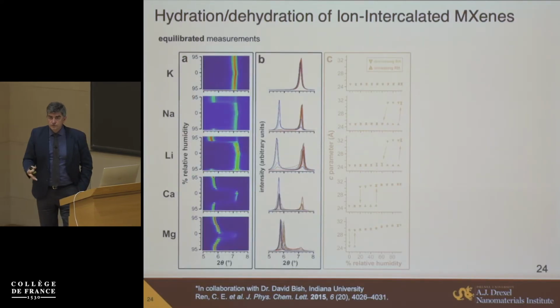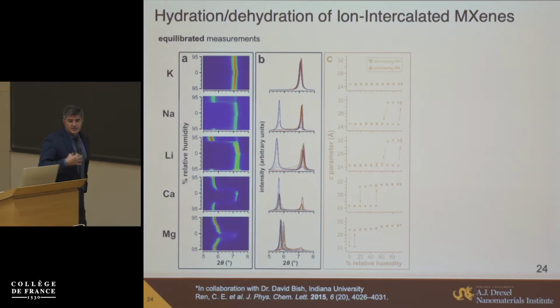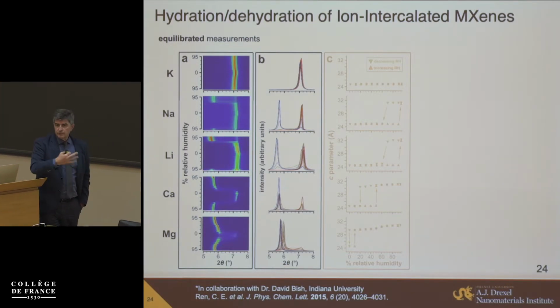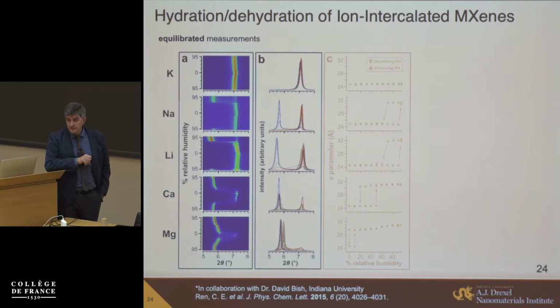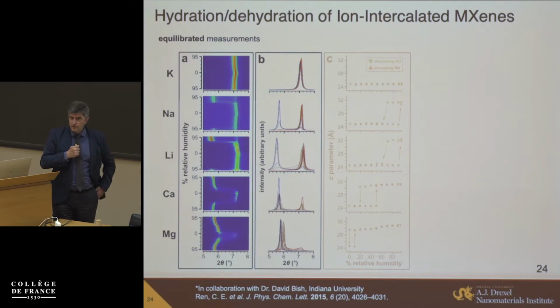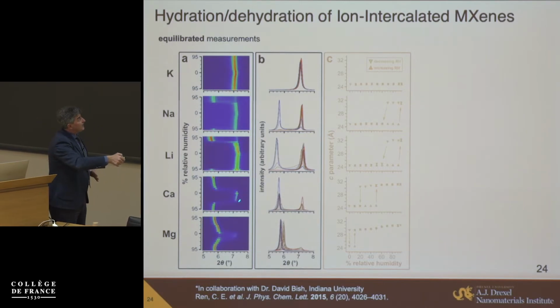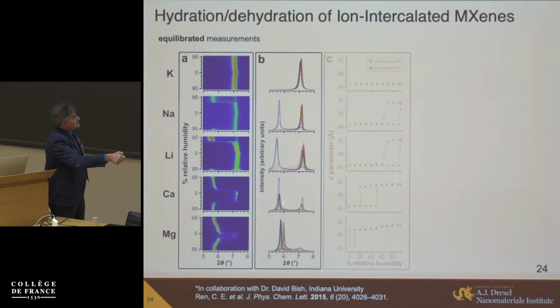Now, what is also interesting, it's not like you can continuously add solvents, say water molecules, if you talk about an aqueous system, and ions. If you have in this system ions and solvent molecules, water actually will go monolayer by monolayer in stepwise function. If you look at changes in position of the X-ray diffraction peak, when you change the humidity from 0 to 95% here, you will see there is no continuous change. There is a peak here corresponding to a monolayer of water molecules, and then it jumps to 2 layers of water molecules. And it will be the same here.